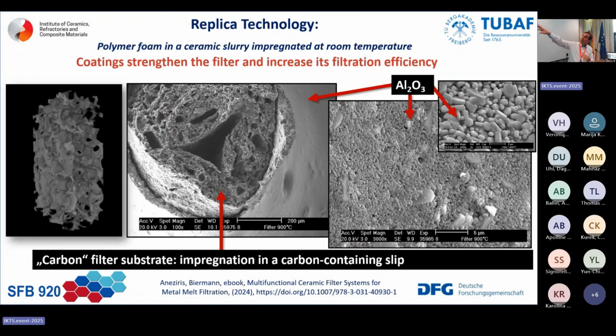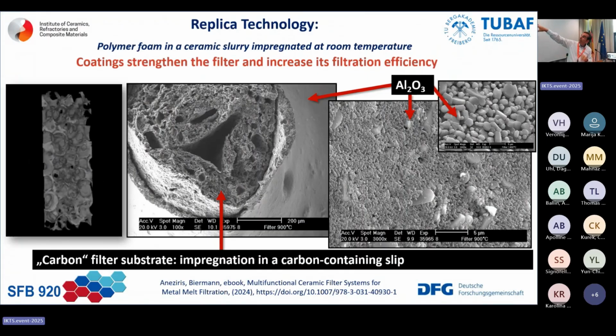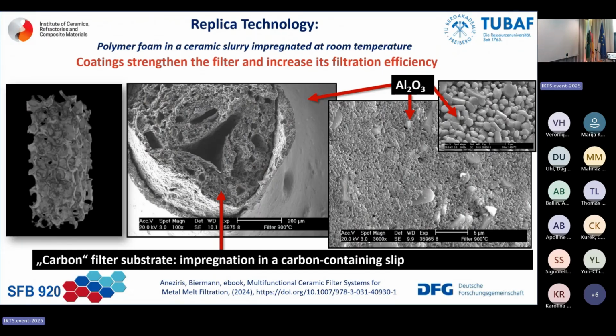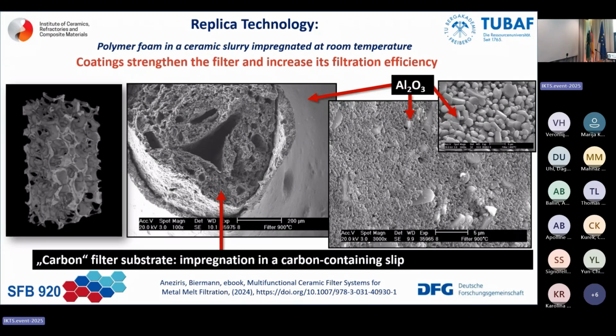Of course, you have to design the structure. You have to put in the carbon bonded alumina. So this is a carbon bonded alumina. You have to put on the top aluminum oxide, but you have to pay attention not to sinter it very tight, because you want to breathe with the melt, to have an exchange with the melt.